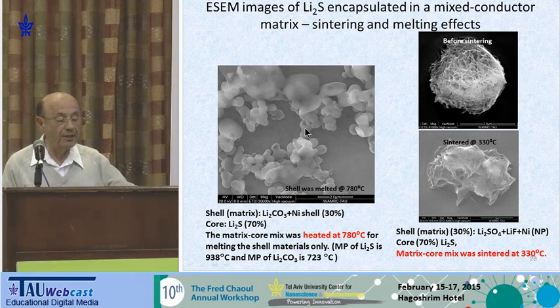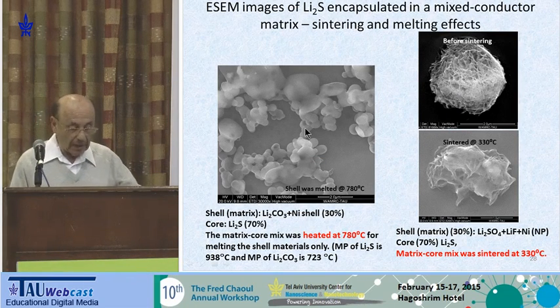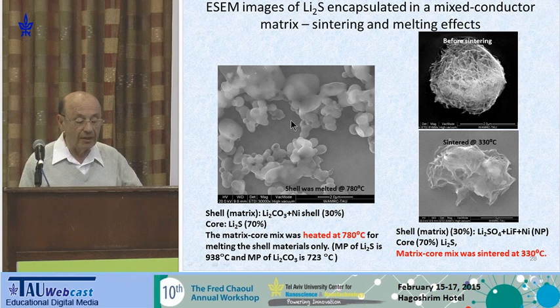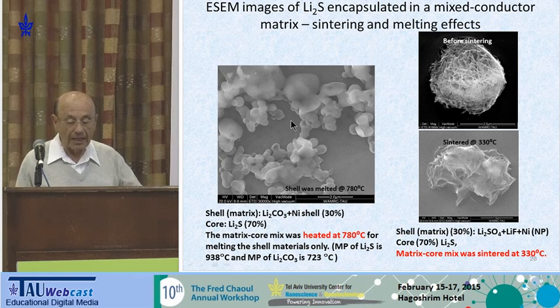So here you see SEM images, and some of it on the left side is what we do. We have two options. One, to completely melt the shell without melting the lithium sulfide, because lithium sulfide melts at above 900 Celsius, and we're using shell that melts at about 700 or less. Or the other one is just sinter it.